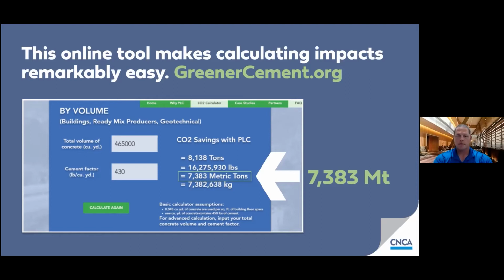This is a concrete pavement project on Interstate 10 out near Blythe that's slated to use 465,000 cubic yards of concrete, so it's a big project. And I estimated 430 pounds of cement per cubic yard, probably be closer to 500 pounds of cementitious when you factor in the fly ash that Caltrans tends to use. And the estimate we came up with is 7,383 metric tons of CO2 savings.